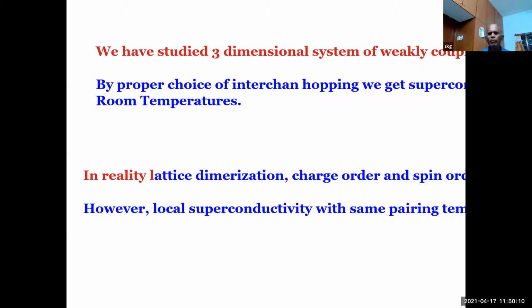These are very good, we have good experience of this in cuprates because there is a family of cuprates. If you look at the normal state, you can't distinguish between them, whereas if you look at TC, they swing from 5 to 160 Kelvin. What is the reason? The reason is competing orders like charge order, spin order, stripe order, which tend to distort the octahedron, localize charges, and do not allow Cooper pairs to escape and delocalize, go into a coherent state.